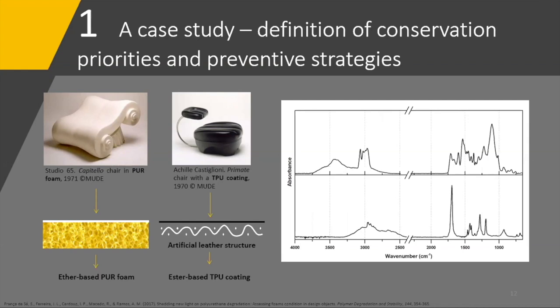From this result, we could be aware that the first object is more susceptible to UV light and radiation and oxygen, whereas the polyurethane in the second one is more prone to suffer from hydrolysis. Moreover, as in the first case the foam is covered by a thick white paint layer, so it's more protected from light, radiation, and oxygen renewal, this object was not put at the same level of priority as the second one, in which the black polyurethane coating is completely exposed to air and therefore less protected. So in sum, different priorities in the management plan of the museum collection were established, as well as different preventive measures.